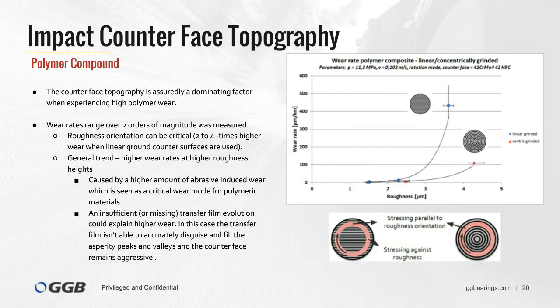This shows you the wear performance of a polymer composite as a function of the counterface topography. It is clearly visible that the counterface topography is a dominating factor when experiencing high polymer wear. High wear of a polymer is often accompanied with a shorter life cycle and thus critical for the application. So the experiment showed that wear rates were measured in the range of two orders of magnitude.